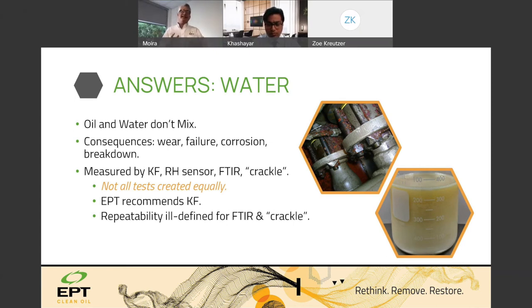Online sensors are great, but they don't replace traditional oil analysis, okay? So if you have a sensor on site, the values are going to change according to the temperature of the oil. If your oil is at a constant temperature, make sure you do check that against lab analysis so that you can understand what the RH means, okay? Relative humidity is RH, but that's not going to normally correspond directly with a part per million. But you might be able to establish, well, if my RH is 40% and my lab analysis is telling me that my water is 300 parts per million, you can start getting an understanding of what that sensor is telling you in real life, okay?